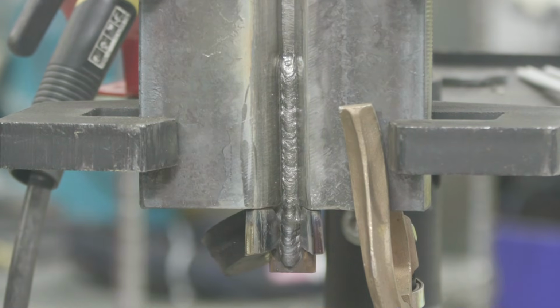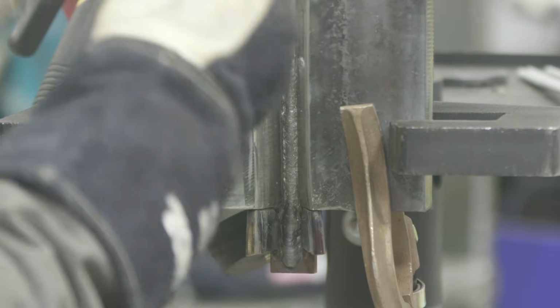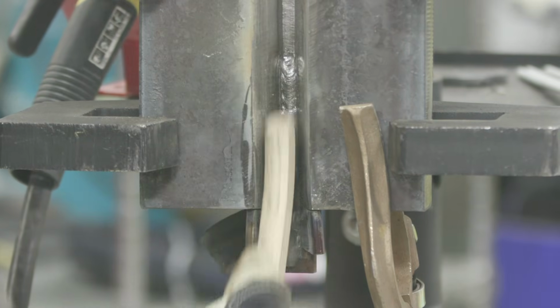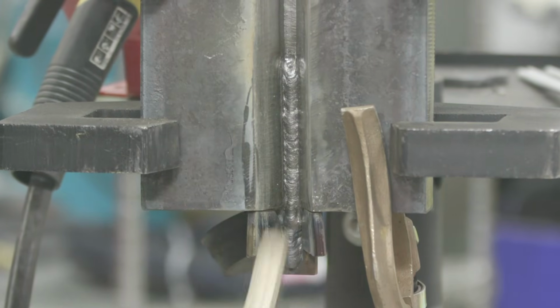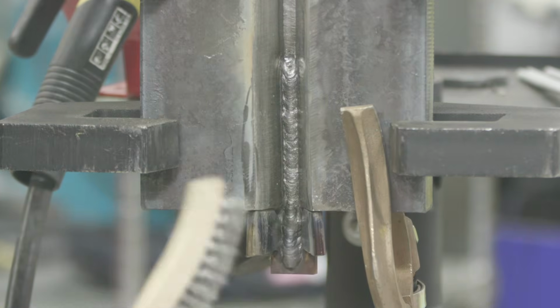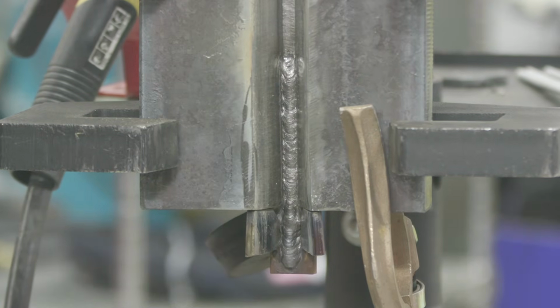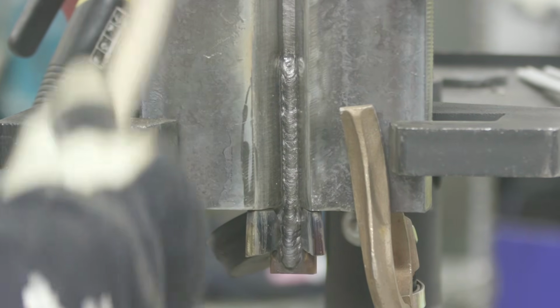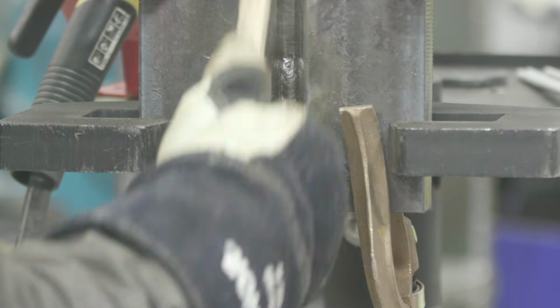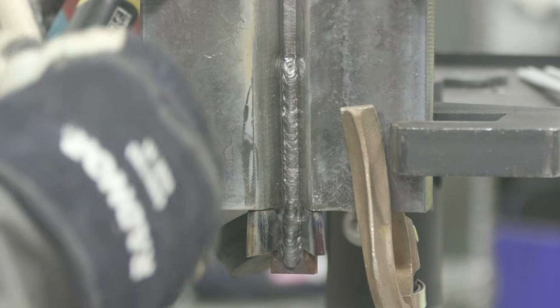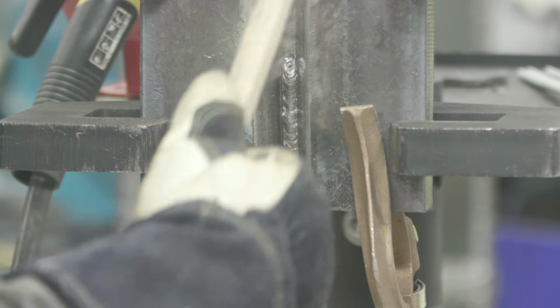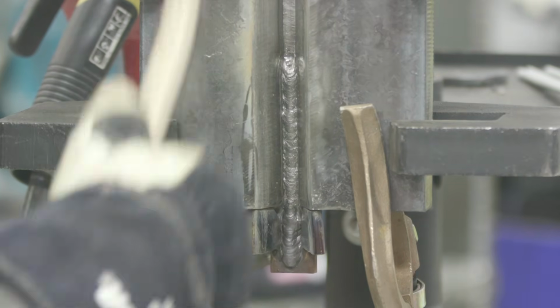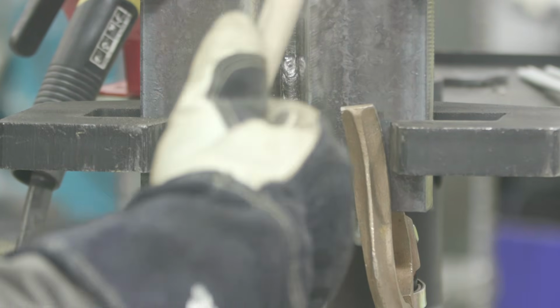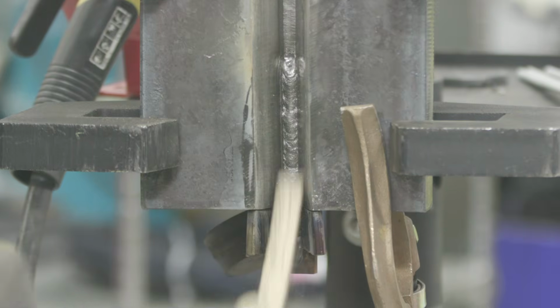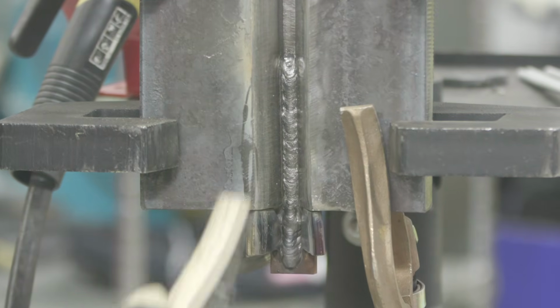I'm cleaning up with this little Weiler toothbrush here because I want to get all the way into that groove. The best time to clean this stuff is right after you get done welding. Go ahead immediately and start cleaning it. That slag's going to come off a lot easier while the piece is hot. If we wait between passes to let the plate cool down a little bit more to where it's manageable, not necessarily on the root or the hot pass, but the subsequent passes we're going to be putting in here, we want to make sure we do all our cleaning immediately after the welding.